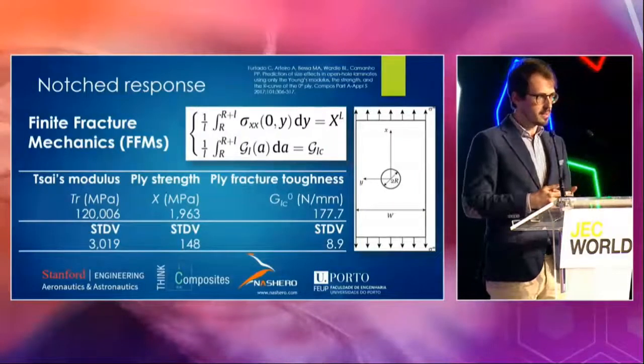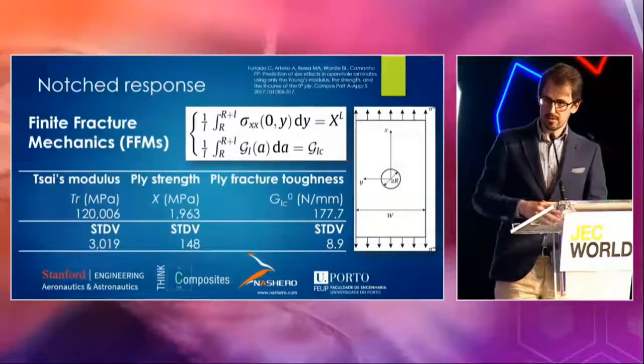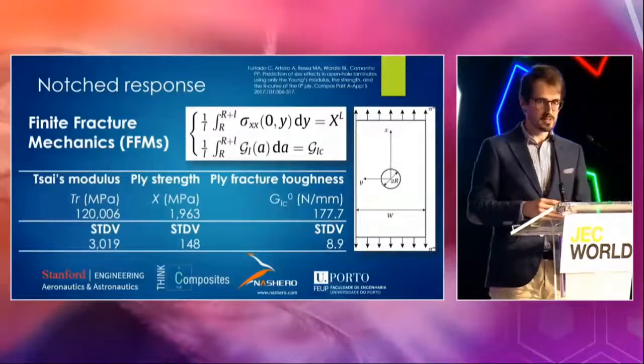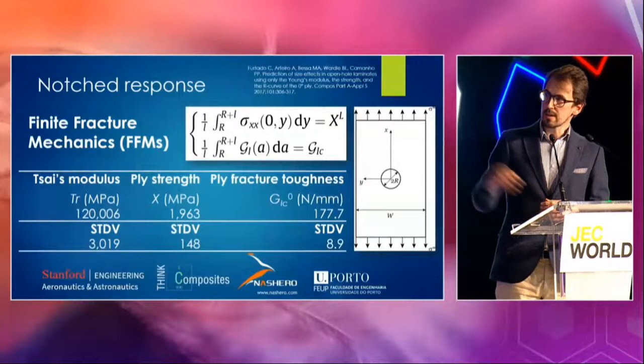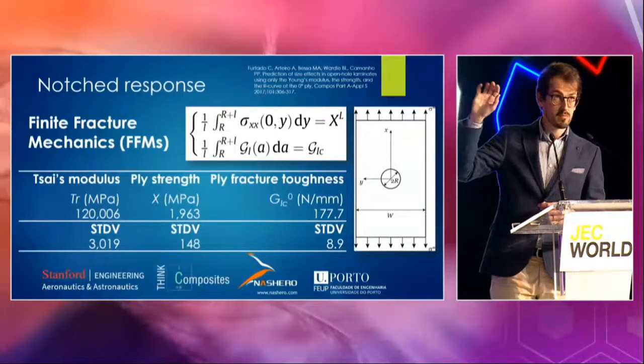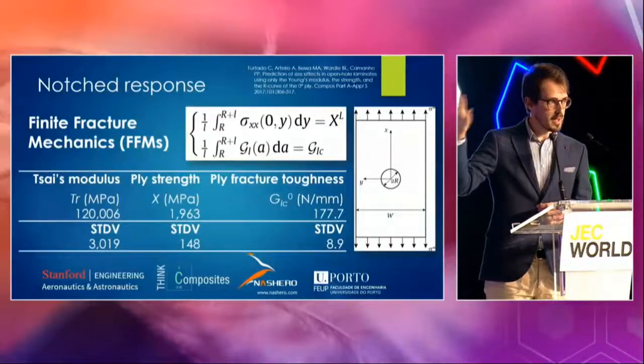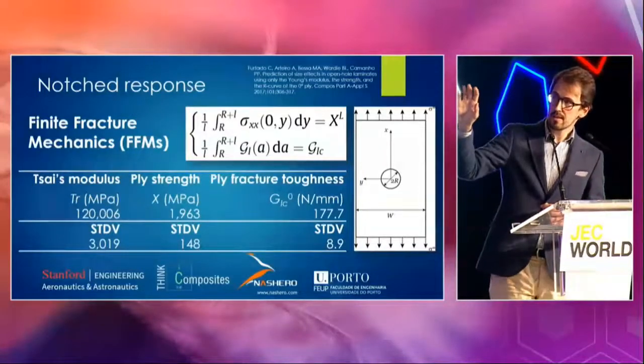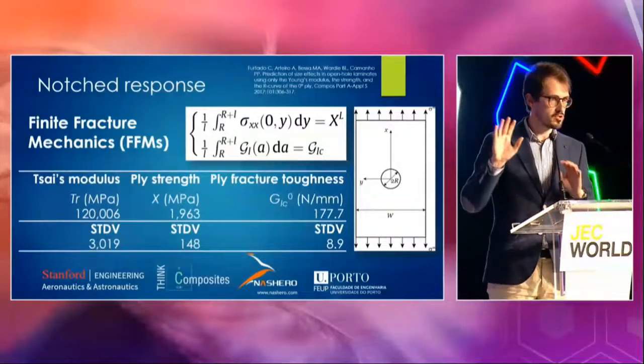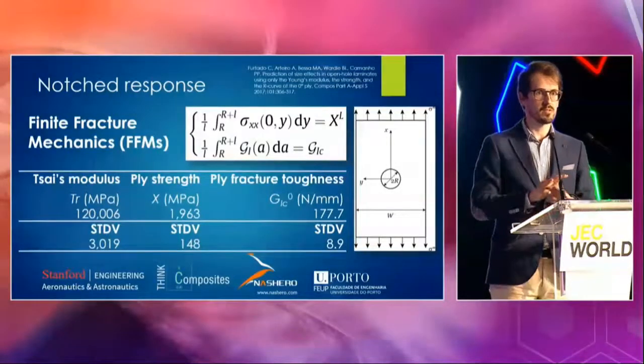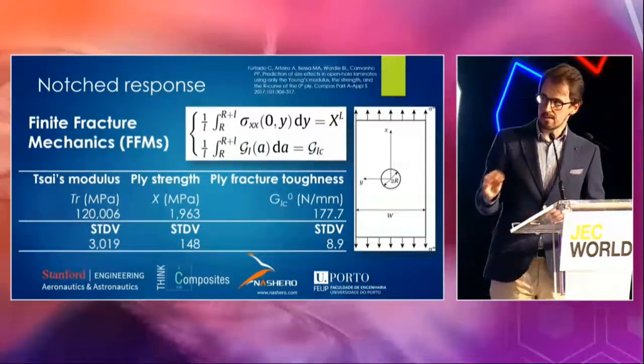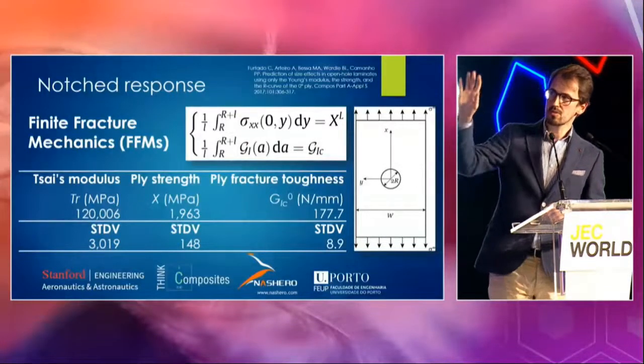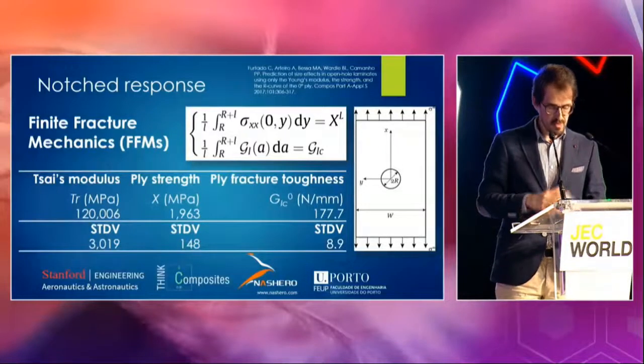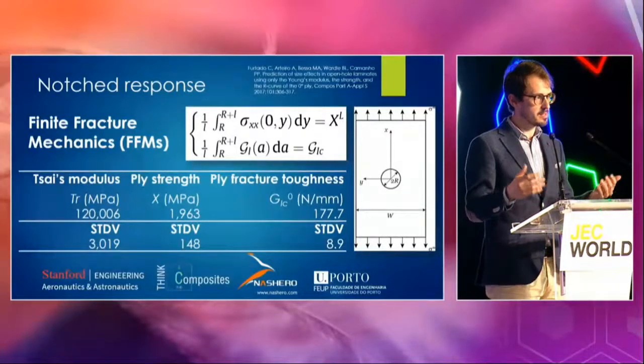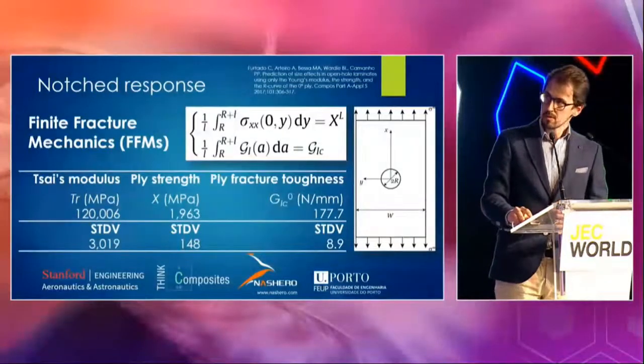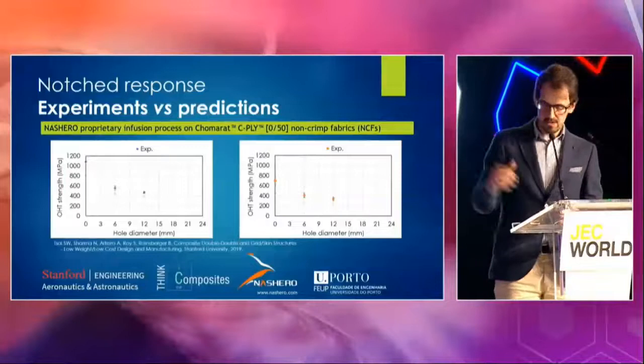Using other analytical technologies, including Tsai's modulus or the trace of the in-plane stiffness matrix, as Naresh was saying earlier, you can actually derive the laminate strength and the fracture toughness of any laminate using the ply strength and the ply fracture toughness. Okay, so you just need the strength of a unidirectional 0-degree ply and its fracture toughness as well, and then with Tsai's modulus you can actually derive those properties, and you can do that for legacy quad laminates, and you can also do it for double-double. So let's see then how the predictions come out.